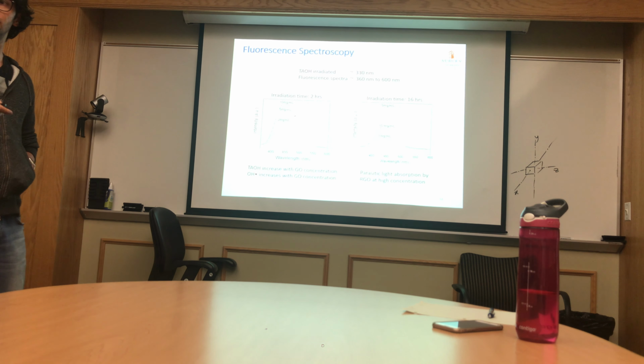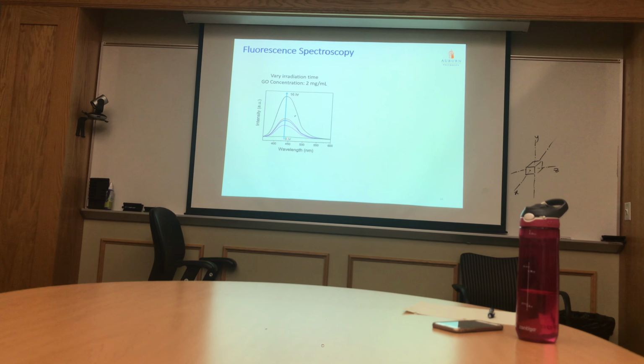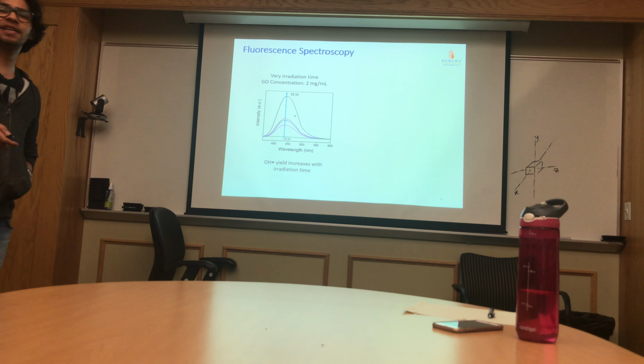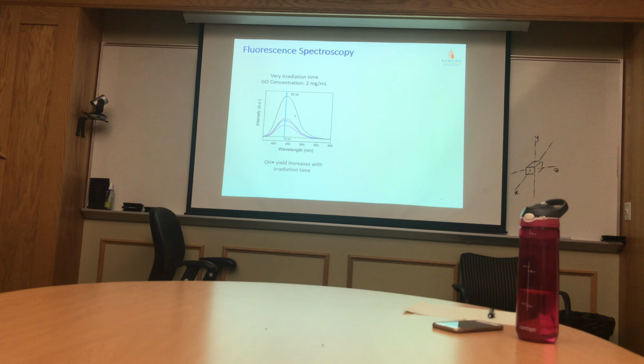One more experiment we did was where we varied the irradiation time while keeping the GO concentration constant, and we realized that as the time is increased, OH yield is increased. So this represents the degree of reduction of graphene oxide. As it is reduced, we get more and more OH free radical.